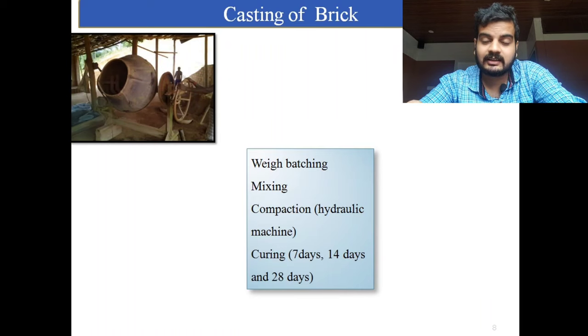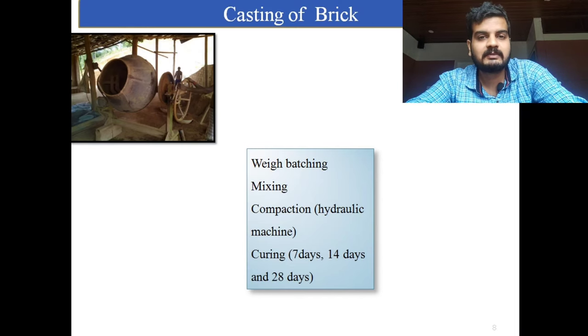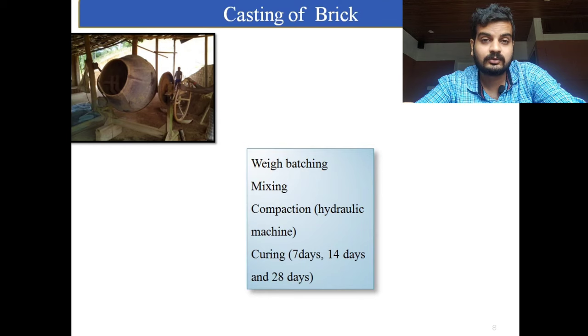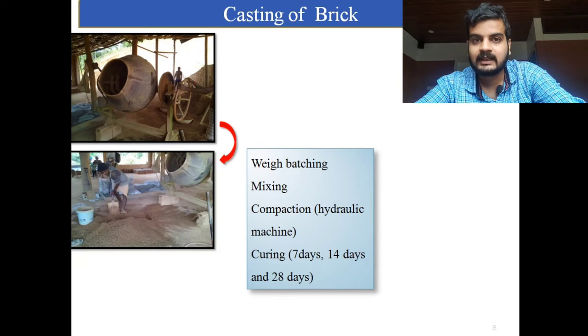Here weigh batching is done. We have to weigh the materials, like how much soil is required, how much cement is required, like that. And after weigh batching, around 6 to 8% of cement is added in this kind of bricks, and also the chemicals. And next, you can see there is a mixer. A mechanical mixer should be used, to get a homogeneous mixture we should use a mechanically operated mixer.